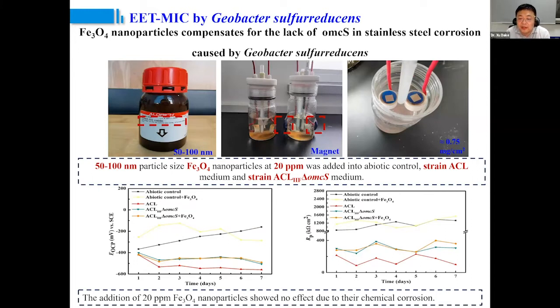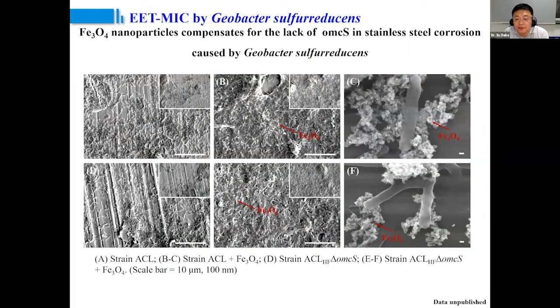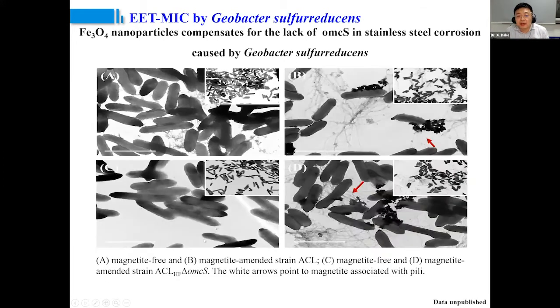We found that the addition of nanoparticles doesn't influence the environment, doesn't influence the corrosion of the sample. Then we do add the Geobacter sulfurreducens. We can see the nanoparticles are well associated with the bacteria. This is the SEM image, and this is the TEM image. Without nanoparticles, we can see some pili. When we add nanoparticles, the nanoparticles are well associated with the cell membranes, and the nanoparticles may even facilitate the production of pili.